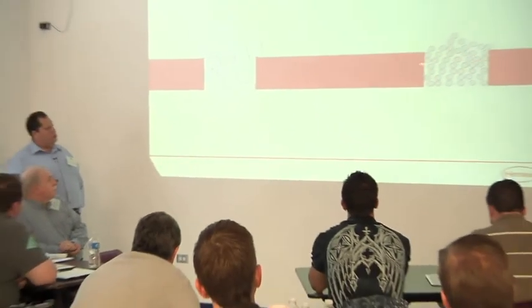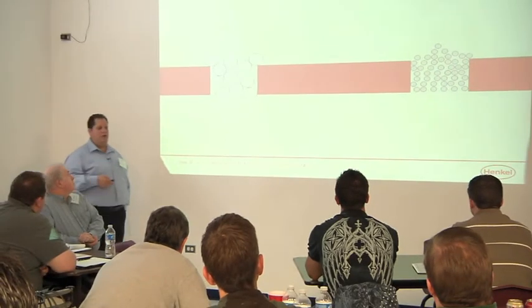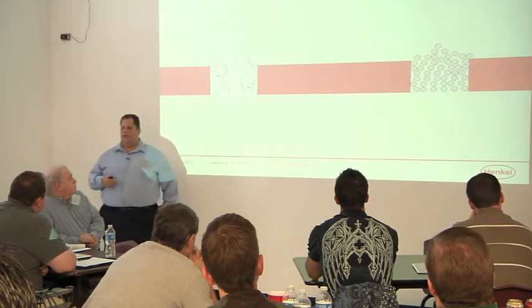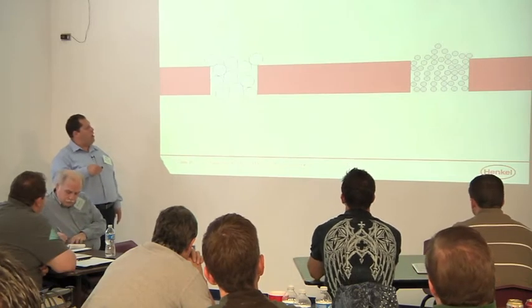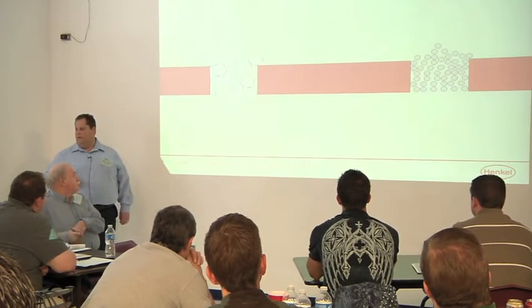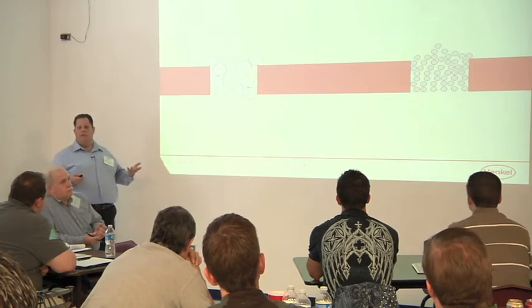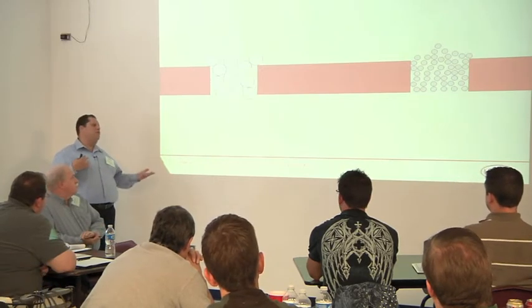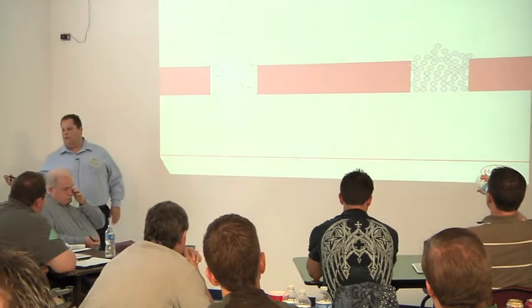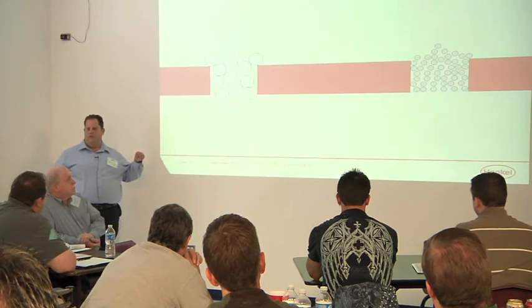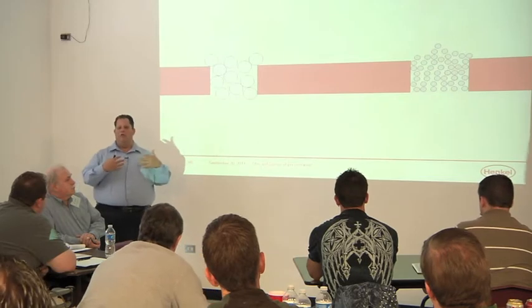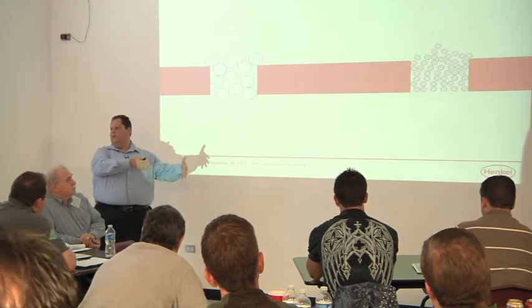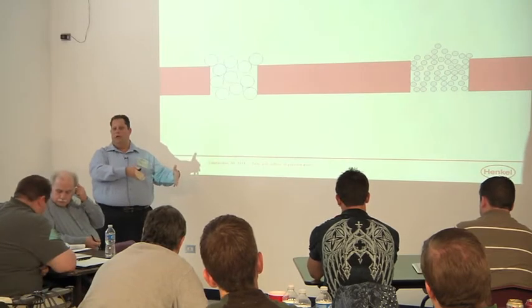Graphically here, the bigger spheres don't pack as well as the smaller spheres pack inside of an aperture. The better packing you get, the better release you get, and the more even and crisp deposit that you get. Obviously if the aperture was wider and these packed really well, you wouldn't need to worry about that. When we talk about particle size and why it's important - most people think: I've got to do 0402s or 0201s, so I have to use Type 4. Well, maybe not. How thick is your stencil? What's the aperture size? Are you printing home plate? Are you printing crowns? There's a lot more that goes into it than just this type of component needs this particle size.